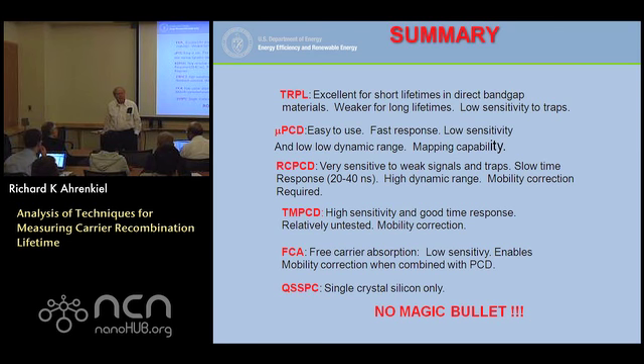But I always go that the lowest injection is probably the most applicable and meaningful, except in these cases where there are some insignificant things like shallow traps that maybe you have to fill before you get to the real low injection lifetime. But it's not automatic. You turn it on and you play with all the stuff and you look at it, watch it change, and then work till it makes some sense to you.